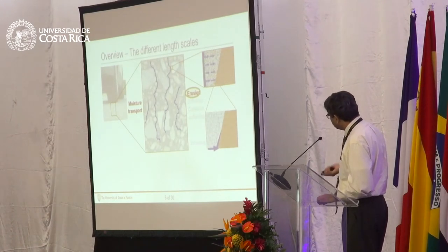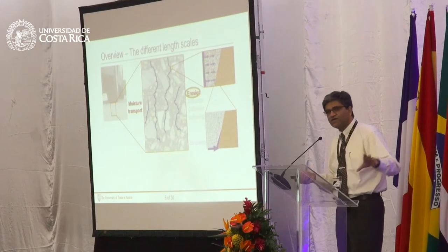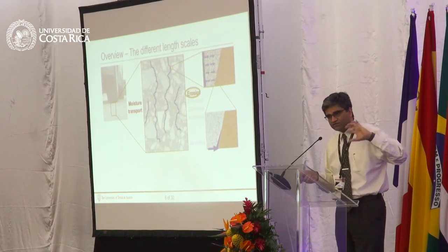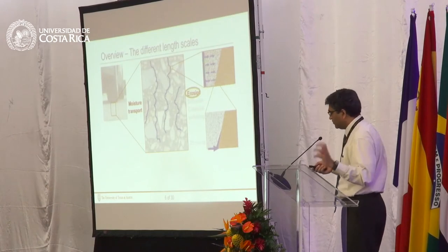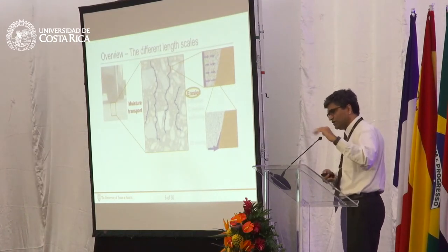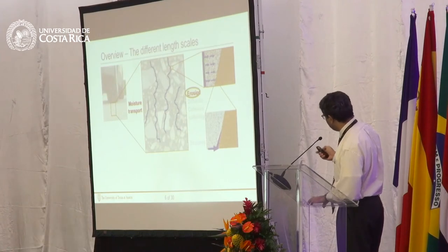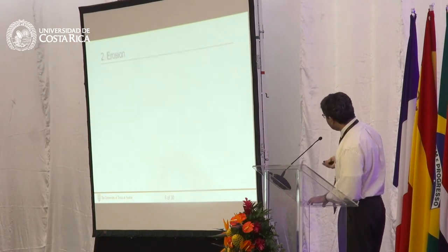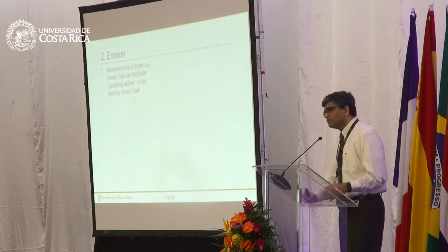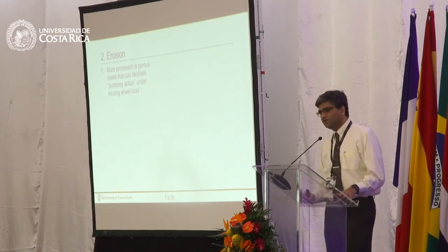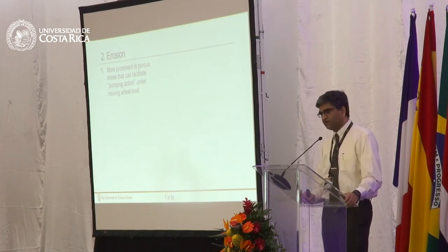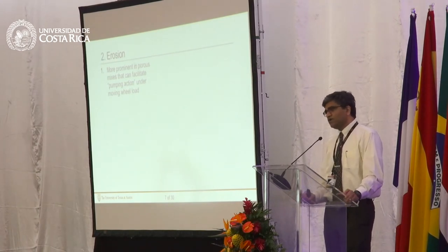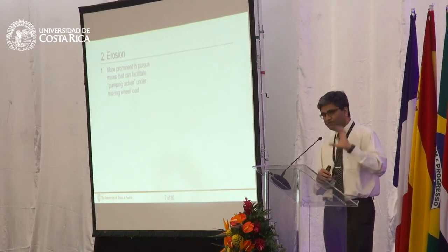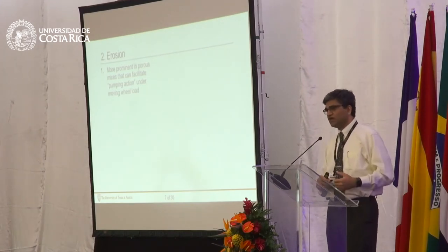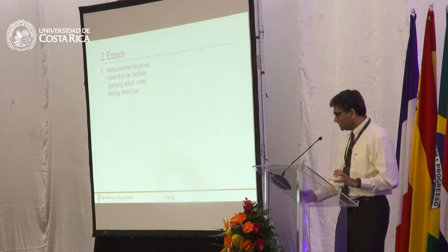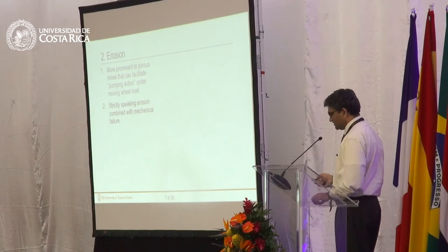Let's go to the second part, erosion. Once water gets into the mix, okay, that's how. So we have air void structure, we have distribution of those air voids, and basically that influences the relative humidity and moisture gradient that drives water in. Once water gets in, then you have something called erosion. First of all, this erosion work was from a study by Professor Tom Scarpas at the Technical University of Delft and one of his then students, who is now a faculty member in Sweden, Nikki Kringos, where they looked at this so-called pumping action, where you would have these capillaries and water would move in and out of those capillaries at a very high rate.